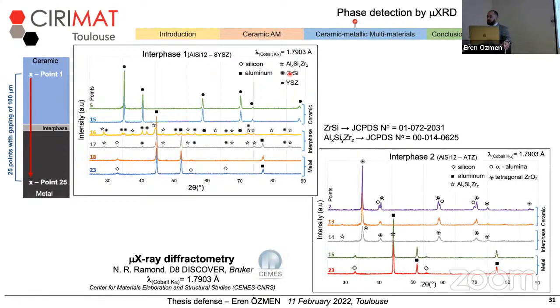When I check the second interface, there is only 1 point corresponding to the interface, which is shown with gray color. There was also the ternary phase of aluminum, silicon, and zirconium. However, the creation of these interfaces and its creation mechanism was still a huge question mark.